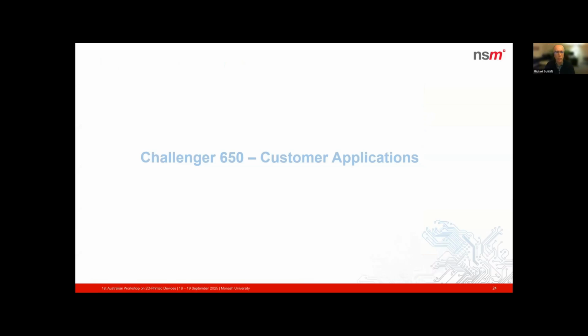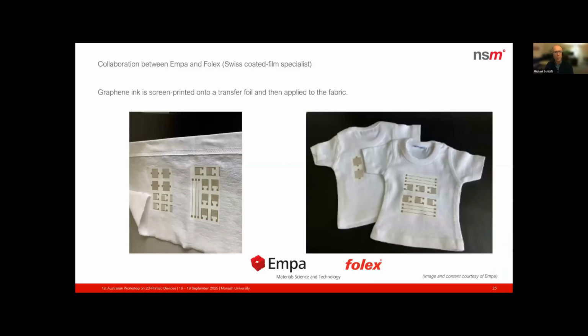And now I want to show you some customer applications with the Challenger 650. The next 6 slides are from our customers. This was a collaboration project between EMPA and Folex, who provided the transfer film. Their graphene ink was flatbed screen printed onto a Folex transfer film on the Challenger 650 at EMPA, then heat transferred to fabric. The long lines are conductivity test tracks, this one here, and the interdigitated patterns are sensor electrodes.